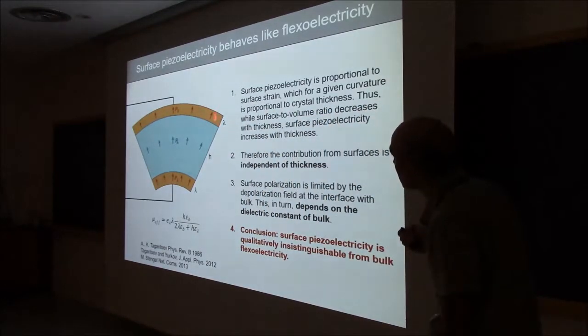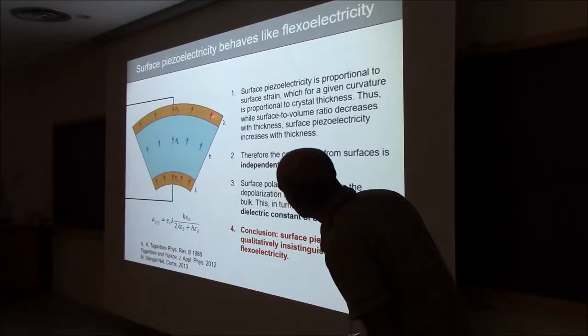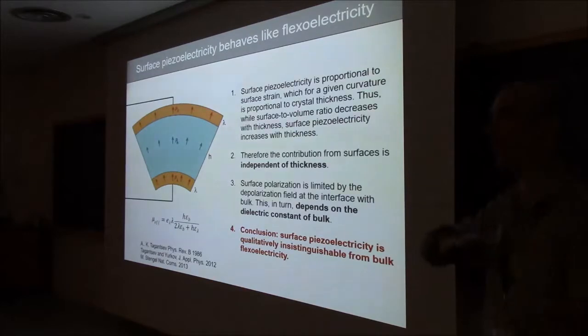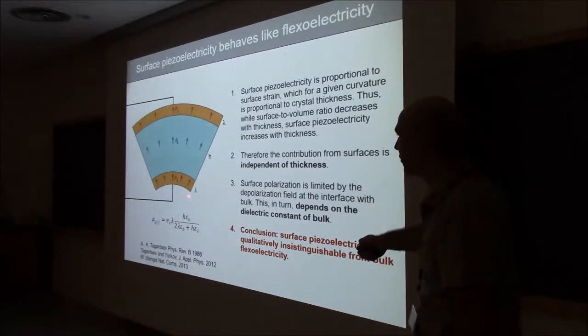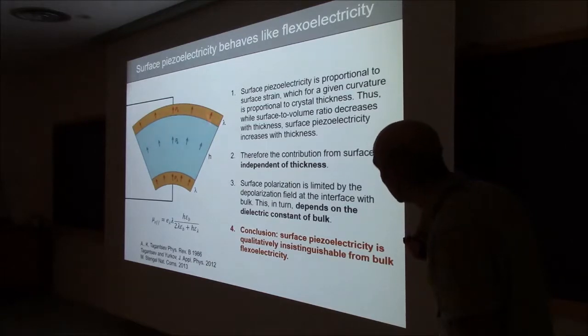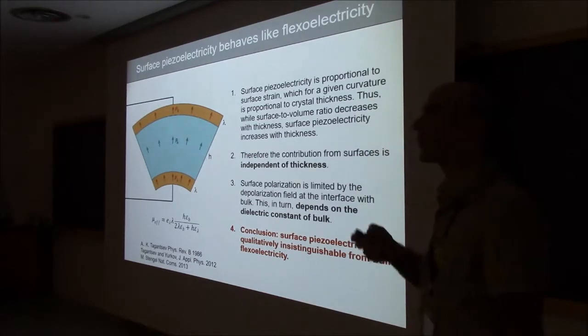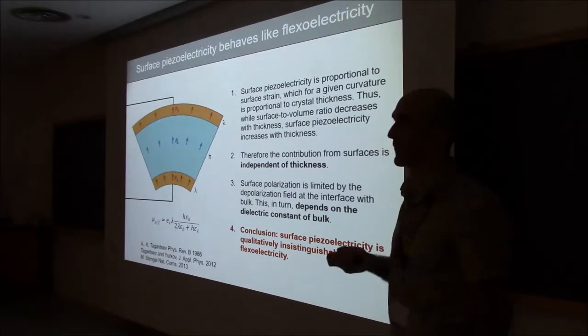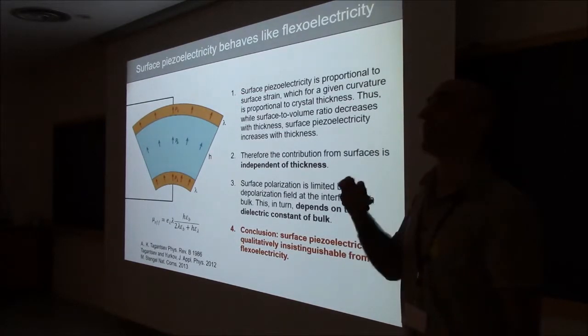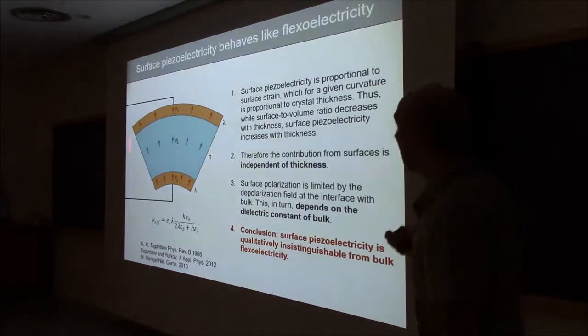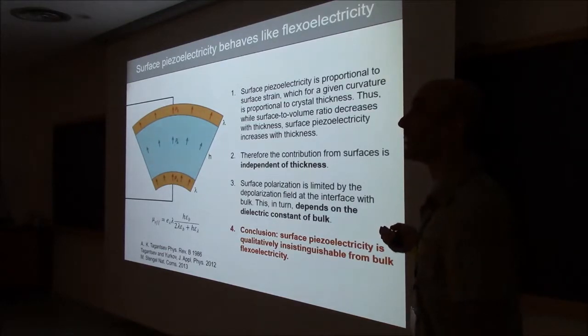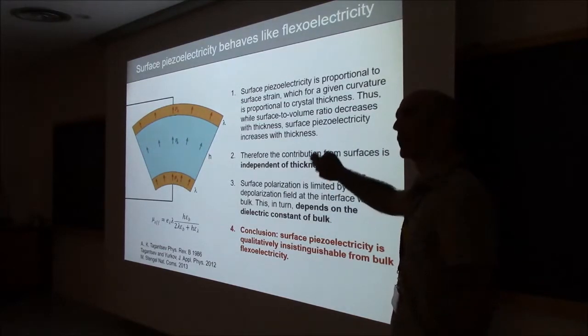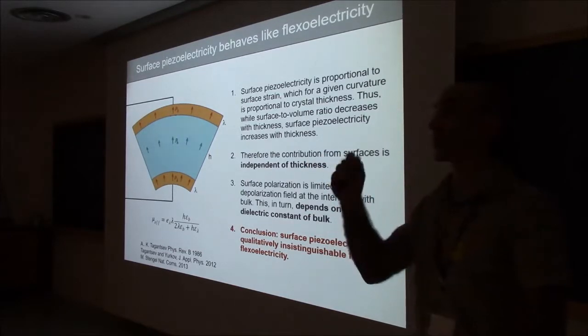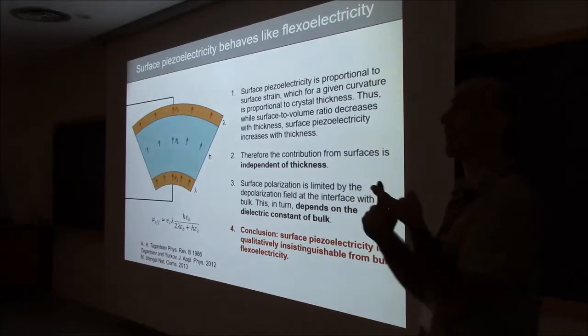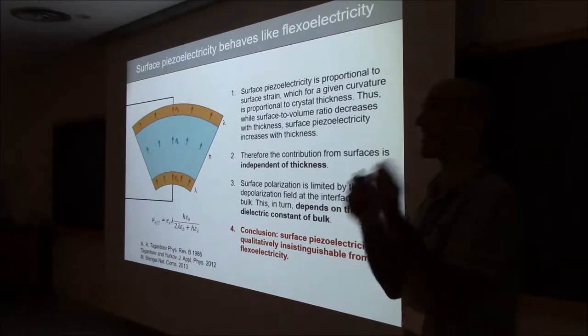Moreover, when you try to polarize this, if you don't polarize that, then there's going to be a polar discontinuity. And you don't like that. You know, you want the displacement vector to be continuous across your crystal. So if you try to polarize the surface, the bulk will also try to polarize itself in order to keep a constant displacement vector. How much this polarizes depends on its dielectric constant. So the higher the dielectric constant of the bulk, the better you'll be able to screen this polar discontinuity, and so the bigger the net contribution from surface piezoelectricity. Which means that surface piezoelectricity is A, independent of thickness, and B, proportional to the dielectric constant. Exactly the same as bulk flexoelectricity.